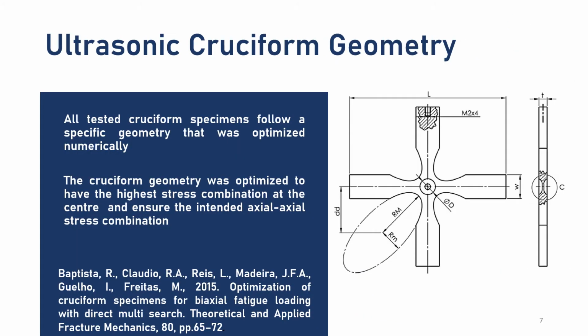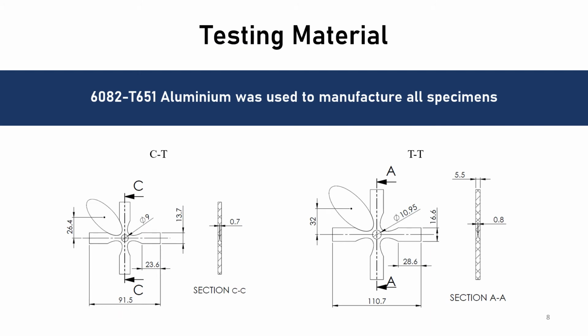Now all cruciform geometries follow one optimized geometry made by Batista and his colleagues in the paper that we present here on the left corner of the slide. This geometry was optimized to have a higher stress combination at the center, the fatigue testing region, and ensures the intended axial-axial stress combination in the same fatigue testing region. Now we made all specimens from the same aluminium, the 6082 T651 aluminium, and made CT and TT specimens presented on this slide.